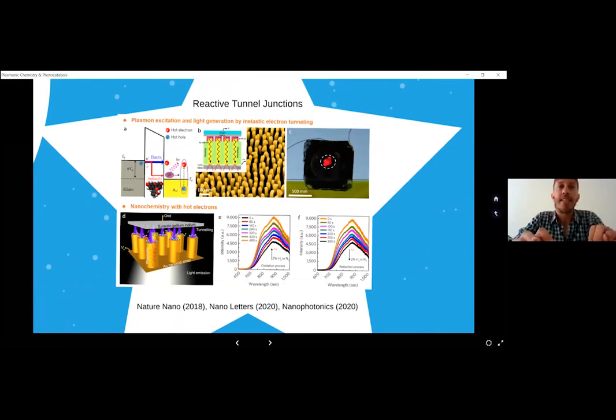One is that they are transferred through the tunnel junction as hot carriers into the gold structures, or the other is that the electrons can be transferred radiatively and excite the plasmon modes in these gold nanostructures. So if we have enough voltage applied across the gap, we have two ways of exciting carriers in the gold nanostructure, either by tunneling of the carriers or by exciting via radiative decay of the electrons.